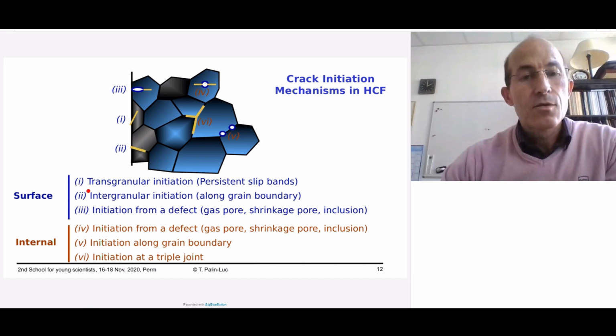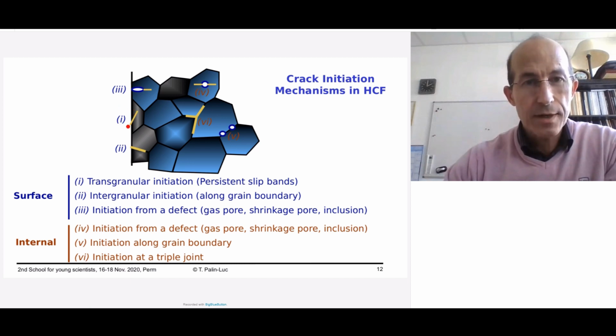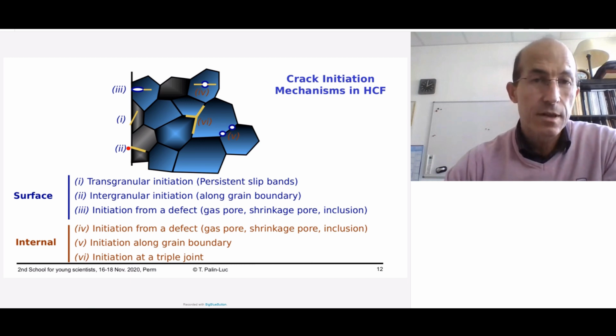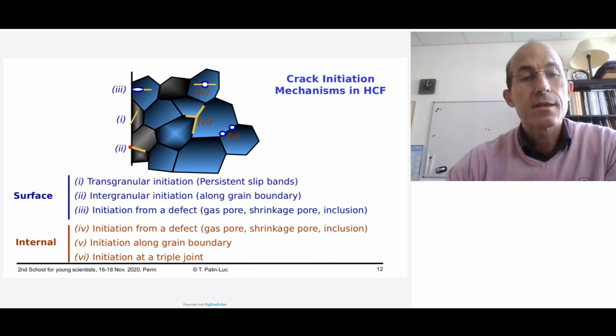There is usually the appearance of persistent slip bands at the surface within one grain, which indicates transgranular initiation. You can also observe intergranular crack initiation, so in between two grains, or along the grain boundary. And it is also possible, of course, to have some defects at the surface, like gas pores for a cast material or shrinkage, or also inclusions in non-pure materials. Non-pure materials are the case of the most common industrial alloys, where there are always some pollutants, some non-metallic inclusions, etc.